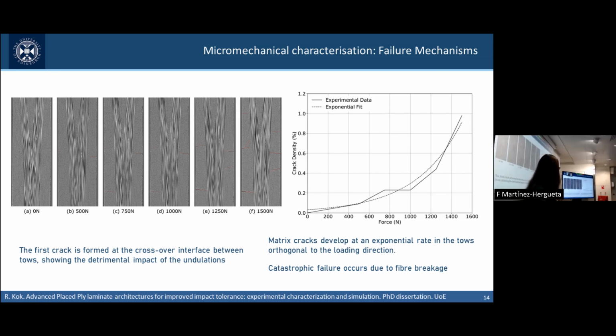What I would say is interesting to appreciate is that the first crack originates exactly at the undulating point. That means that the undulations are going to present strain gradients that are going to have a detrimental impact on the strength of these composites. We can already see that happening here. All the rest of the cracks, maybe on the screen it's easier to see, are all mostly perpendicular.